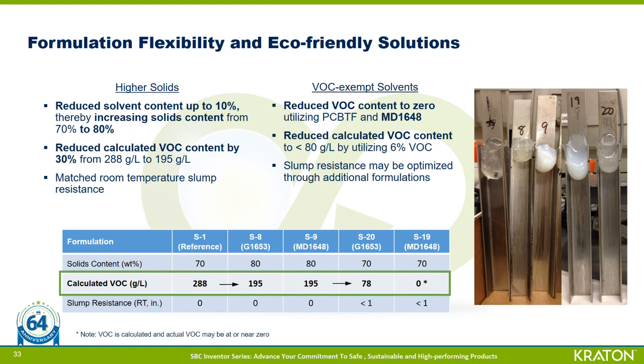So we were able to achieve even lower VOC contents down to 78 grams per liter for G1653 and near 0 for MD1648, which contained strictly VOC exempt solvent and no VOC containing solvents such as xylene or toluene. So we didn't have any of that for the 1648. And the lower viscosity 1648 utilized, again, all VOC exempt solvents.